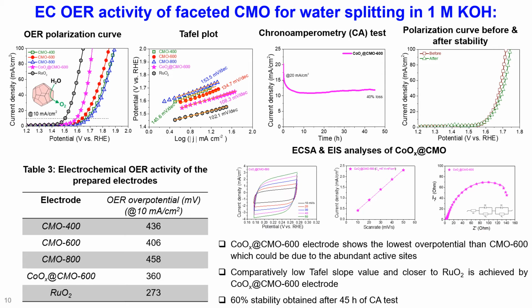Here we can see the lower Tafel value of 108.3 millivolt per decade has been obtained for CoOx@CMO 600 electrode, which is closer to the ruthenium oxide electrode. And then the chronoamperometry test for 45 hours has been run for the CoOx@CMO 600 electrode. Here we can see there is some loss, that is 40% loss, obtained for the electrode after 45 hours